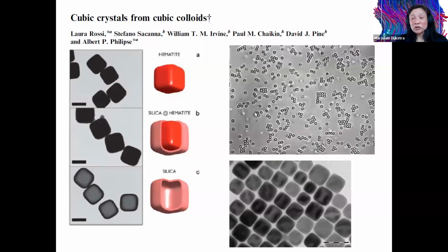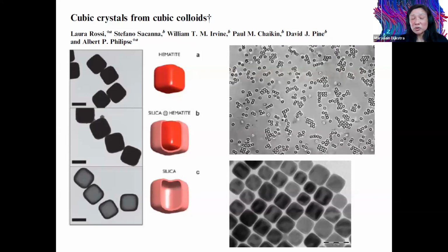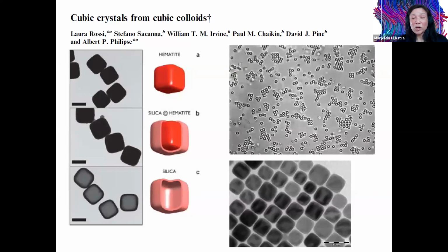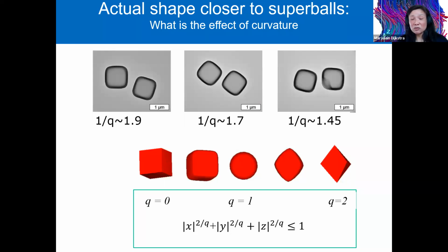And that's why we also decided to look at rounded cubes, where we could go from just straight cubes all the way down to spheres via rounded cubes, and then we could go to rounded octahedra to straight octahedra. And these shapes are just parameterized by this expression here. And so for this system, we also calculated the phase diagram.